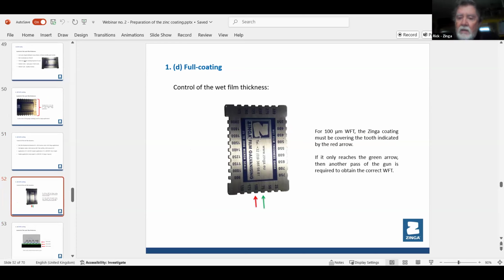This is just again to show you a wet film thickness. If you want 100 microns wet and it hits 75, which is the green arrow, that's too low, so it might require another pass of the gun. That's what we're saying when you're checking. If you take your reading and get 75, clean the gauge, do one more pass, and check it again. And I'll tell you why you check it.